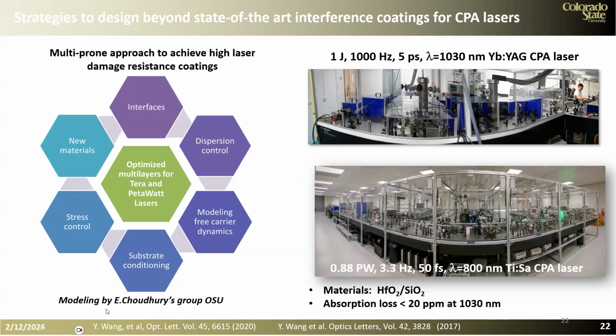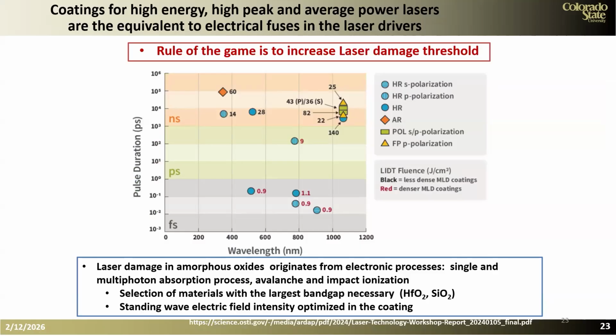We collaborate with a group of Enam Chowdhury, who is doing modeling on these coatings. So the rule of the game on coatings for high peak and average power, near infrared, even UV lasers, is to increase the laser damage threshold. What I show here, a picture from the report that we wrote in the DOE BRN, is that the laser damage threshold is dependent on pulse duration and on wavelength. Notice, this is the femtosecond range, this is the nanosecond range. I go from values that are extremely high, 60 joules per square centimeter, at a wavelength of about 400 nanometers. If I come here, there are no results, but the laser damage will be of the order of maybe 0.5 joules per square centimeter. So this is the challenge.